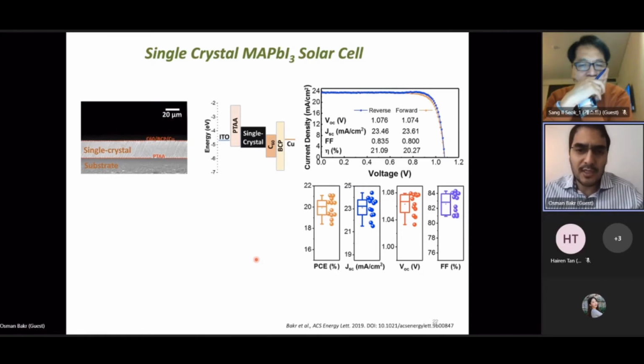So that was a big surprise because normally people thought that you needed very thin polycrystalline cells, very thin perovskite layers, a few hundred nanometers. You couldn't go beyond that. Otherwise, you would lose a lot of efficiency. But here we showed that we have an active layer that's more than 20 microns thick, and you still have a very efficient solar cell, and the fill factor is quite high.